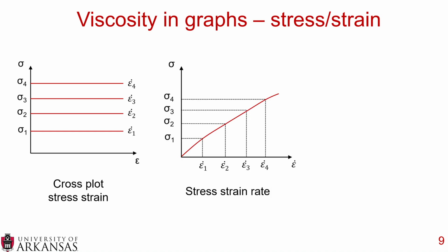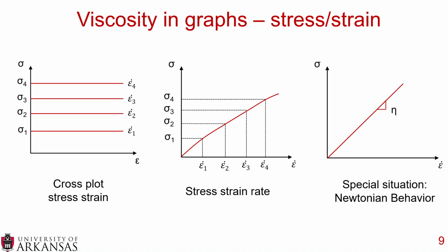Then you can plot the stress against the strain rate, epsilon dot, on the x-axis. And you can see this happens to be a non-linear example. As the stress increases, the change in stress decreases, so it's nonlinear. But there is a special situation where you have a linear relationship, so if your eta is constant, this is a special situation, and this is what we call Newtonian behavior.